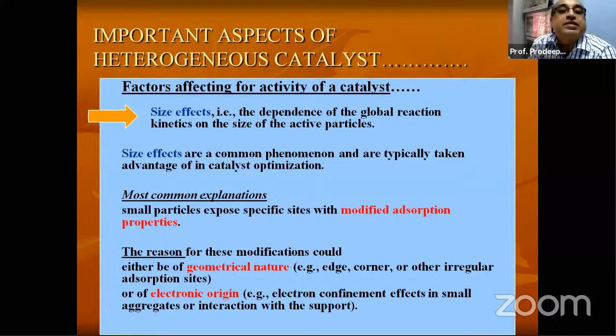Now, what are the factors that affect the activity of a catalyst? It's mainly size effects, and that always depends on the active catalytic metals or catalytic component which are there on the surface of the heterogeneous catalyst. Besides that, the major component is the size effect: the dependence of a global reaction kinetics on the size of the active particles. Size effects are a common phenomenon and are typically taken advantage of in catalyst optimization. So this is typically taken into consideration while we do catalyst optimization.